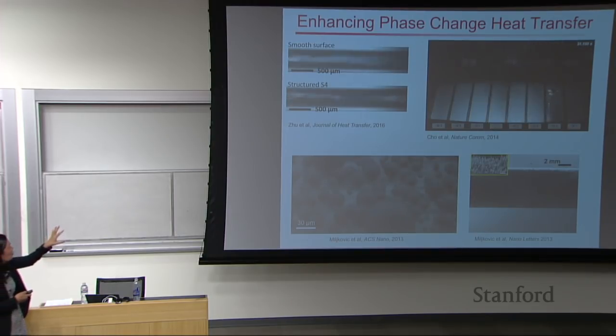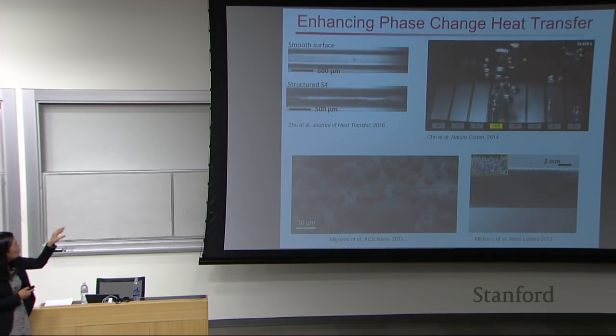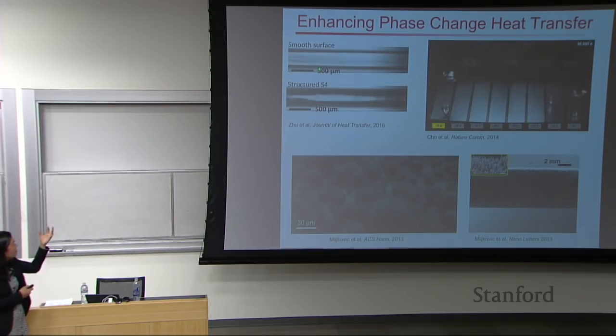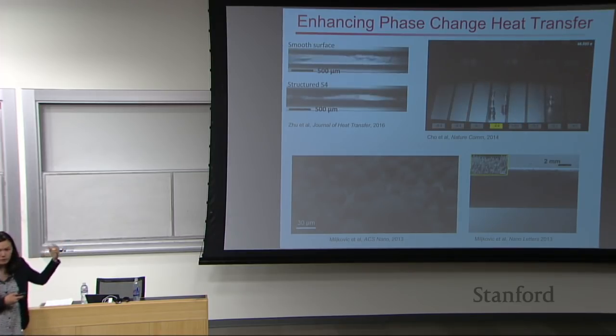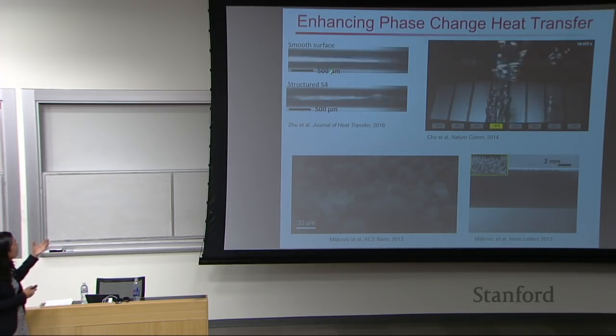She led a lot of the work on thinking about what we're seeing here, which is channel type configurations when heat is applied from the backside, and trying to understand how, when we have these channel type configurations undergoing phase change from liquid to vapor, that affects the flow patterns and the temperature. As you see here from the top, when you don't pattern the surface with any type of features, you have a lot of instabilities from the flow that can lead to local dry out,